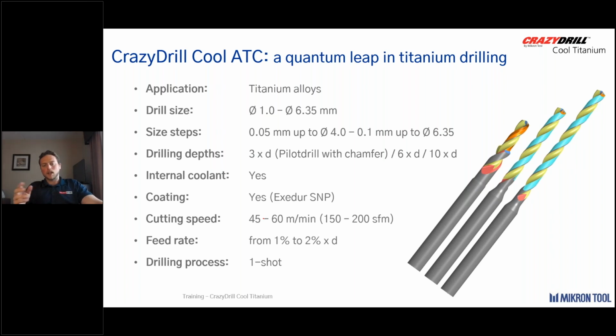Feed rates, that 150 to 200 SFM seems to be a quite happy spot for this tool consistently, given that you have the right coolant and pressure. Feed rates anywhere from 1 to 2%. If you're running oil, if you're receiving that accordion chip, then you would be increasing that feed slightly, but 1 to 2% of diameter is a good place to start. Key factor for this drill, it does drill in one shot.